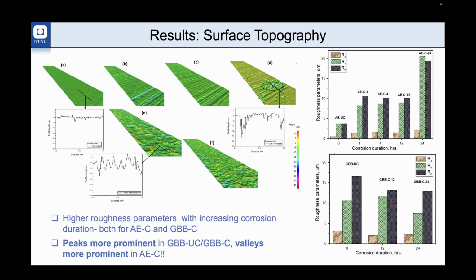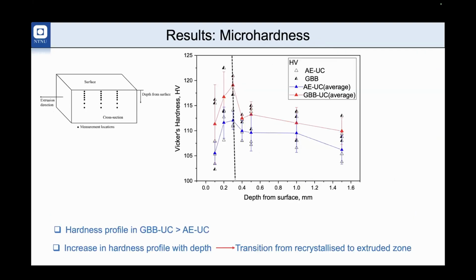And these are the variations of the roughness parameters. You can see that the surface roughness increased significantly as we increase the corrosion duration, especially for the controlled condition. But surprisingly, if you compare this with the glass bead blasted condition, the roughness parameters decrease. Why is that? Because in the glass bead blasted condition, because of the impact of the blasting, the surface roughness itself is quite high, and it is characterized by the peaks. And when the material is corroded again, the height of the peaks decreases. That's why this reduces the surface roughness.